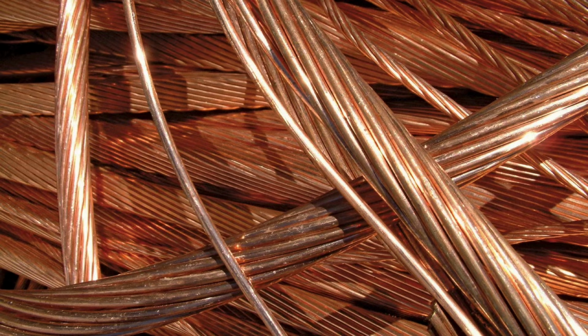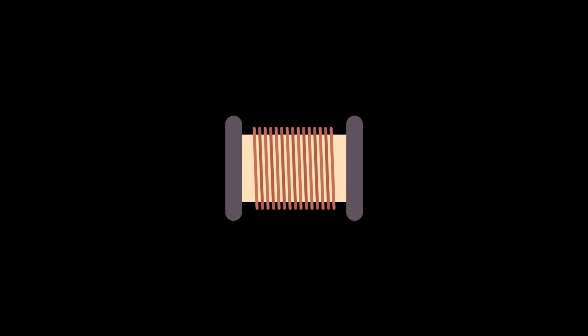At 20 nanometers, copper isn't the best metal to use, despite having the lowest bulk resistance. Copper's bulk resistivity is really good, 1.664 microohms per centimeter. But electrons traveling through it are more likely to deflect and scatter, instead of going in a straight, uninterrupted path, or as they say, electron mean-free path. So at 20 nanometers, the electrons in a copper interconnect are more likely to scatter, making its resistance higher than what other metal lines might have. Weird how nanoscale stuff works, right?